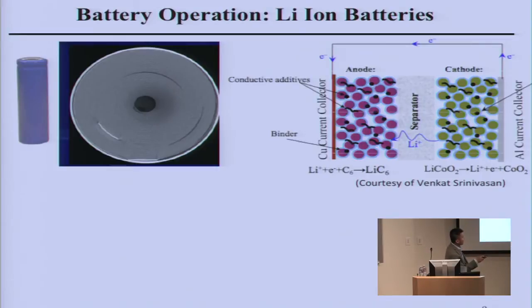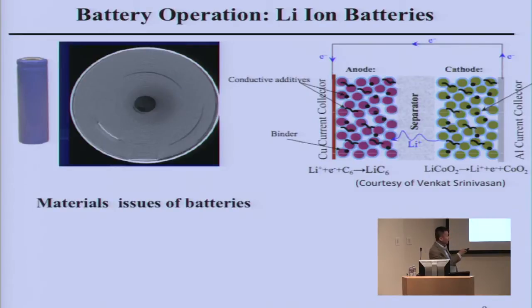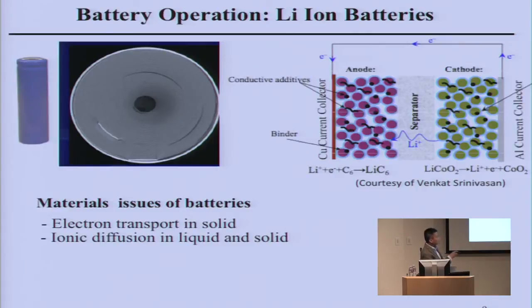During battery charging, lithium goes from the positive electrode, through this liquid electrolyte and the battery's porous separator, to the left-hand side. Electrons move through the outside and then meet inside this graphite carbon, neutralize, and store a lot of lithium and electrons. During discharge, they go the opposite way and go into lithium cobalt oxide. In this process, electrons need to move inside the solid, but not inside the liquid. Electrons inside the liquid just means you have shorting inside. And you need ion diffusion in the liquid and inside this crystal structure, in order to move in and out. But lithium will not go outside, only stay inside.